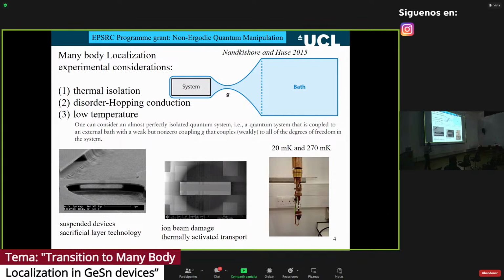And in a disordered system, we characterize the transport properties by hopping. So the charge just hops through either impurity sites or some other sites, hops through the lattice, and that's thermally assisted. The question is, if we take away the thermal bath, so there are now no phonons in the system, what do we get? How can we characterize that system? Does the system form a many-body localized system?